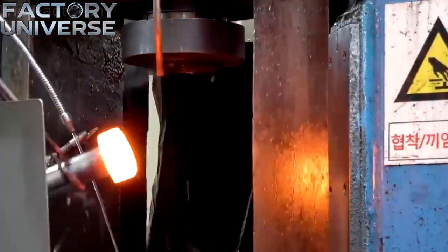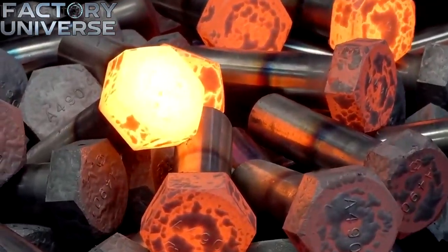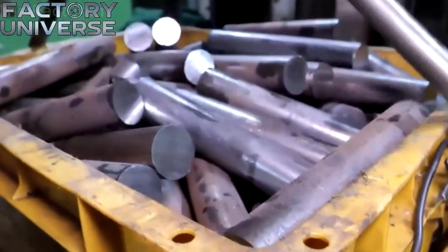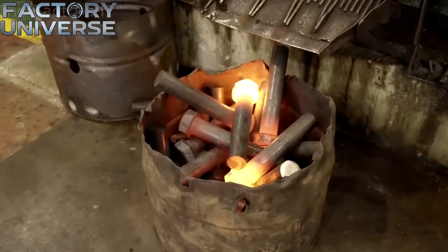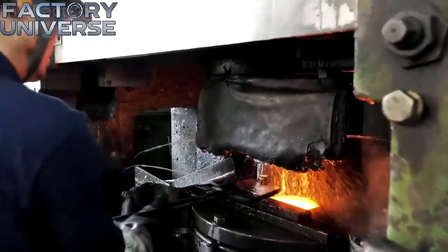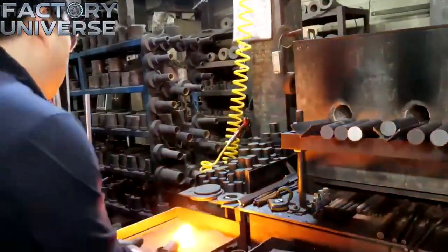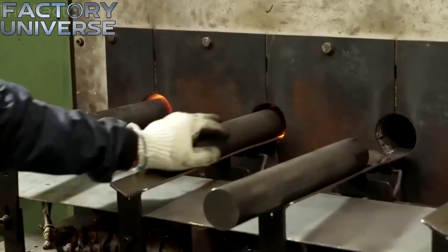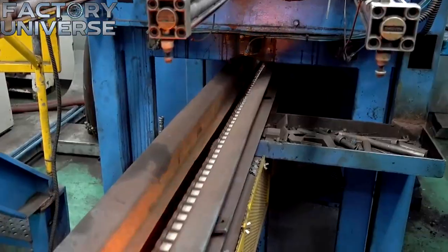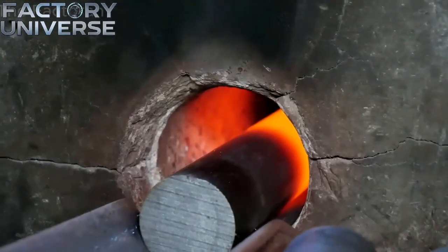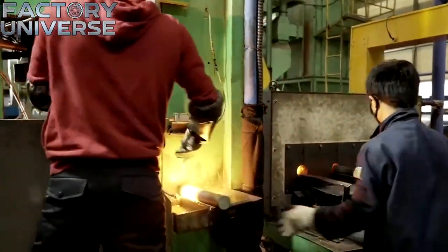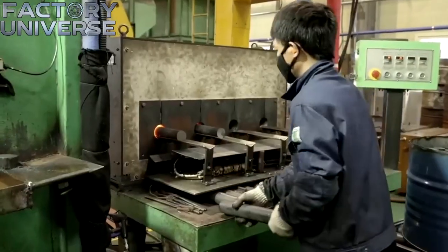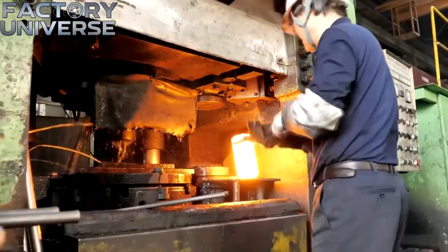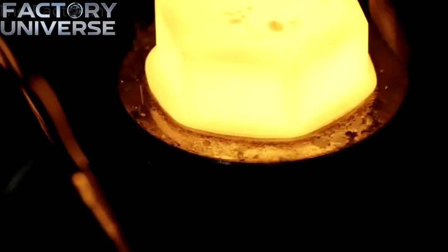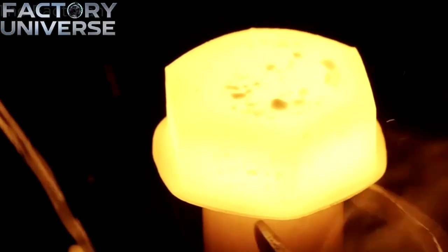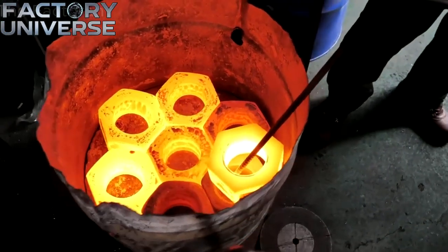Instead of heating the entire length of the steel bar, only the front section passes through a localized induction heating system. Within a span of just a few seconds, the head portion reaches forging temperature and begins to glow a bright orange red. The shank, located behind this section, remains significantly cooler throughout the operation. It seems simple, but in reality, this localized heating method concentrates energy exactly where the hexagonal head must be formed. This strategy reduces overall energy consumption while preserving the mechanical integrity of the bolt shank, which serves as the primary load-bearing section of the fastener.